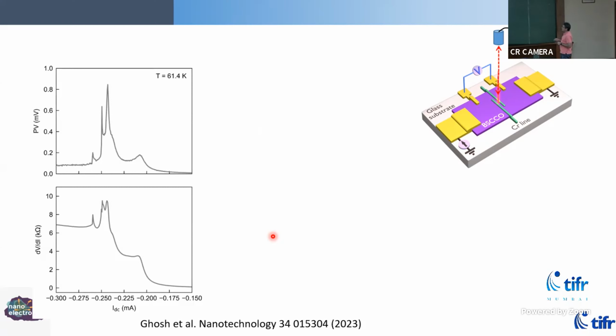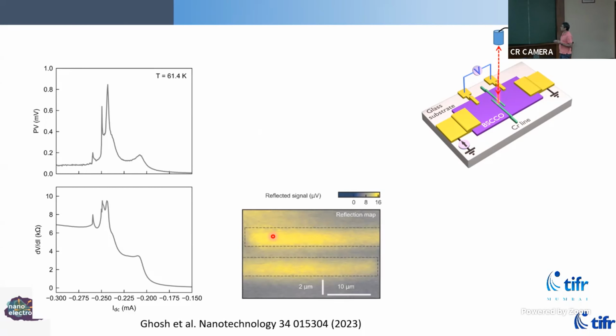So what we showed is that if I look at the resistive transition of a superconductor and I look at the photovoltage response, then we can actually see it. This is about a 20 micron long wire right here. This is the region of the superconductor. This is where we have sprinkled chrome. And we are now imaging its reflected light so that we know exactly where the wire is. So we can shine light, simultaneously look at reflected light, and map out the photo response.